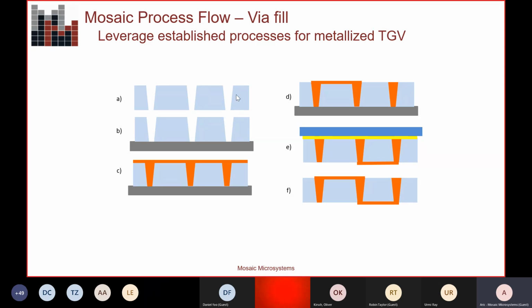So we put a tapered via in the glass and then bond that to the handle wafer. What that does is make it look like a blind via in silicon. Today we limit ourselves to a 35 micron diameter via and smaller. That makes the via fill process faster and less expensive, and it also eliminates the CTE question. If you have very large vias, then you have to worry about the CTE mismatch between the glass and the copper. So by getting a tapered via and having it relatively small, you keep the cost down and you maintain high reliability design rules.